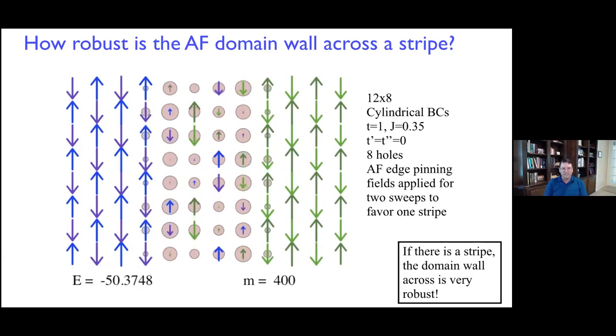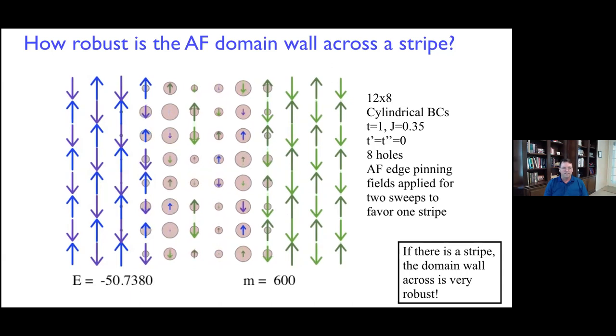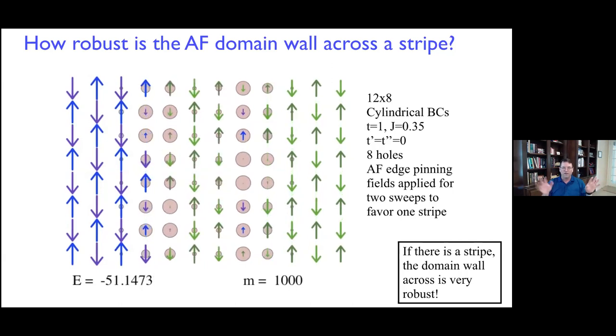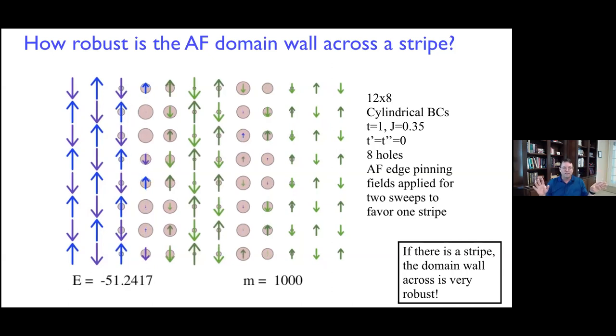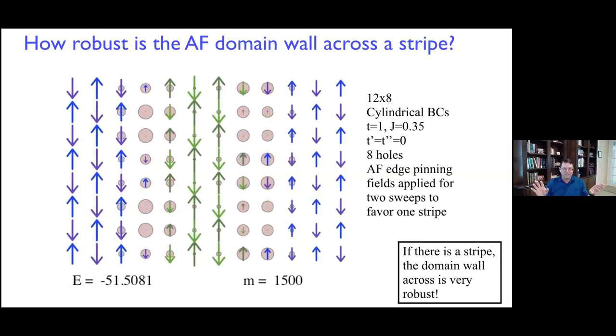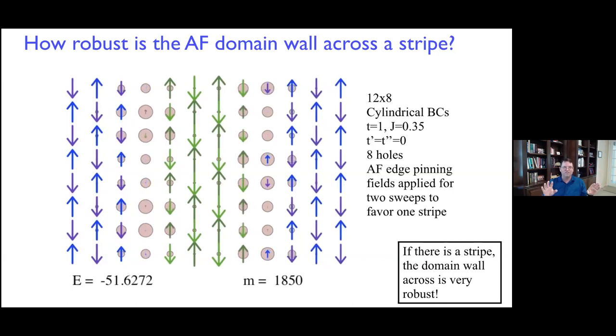Now it's trying to split into two stripes, but it's doing it in a somewhat disorganized fashion because the spins are frustrating it. Through numerical random numbers, it's not quite balanced between the two sides. And all of a sudden it decides that it really wants to make every stripe a domain wall, so it flips the right-hand side. So the conclusion is that if there is a stripe, this domain wall across it is very robust.